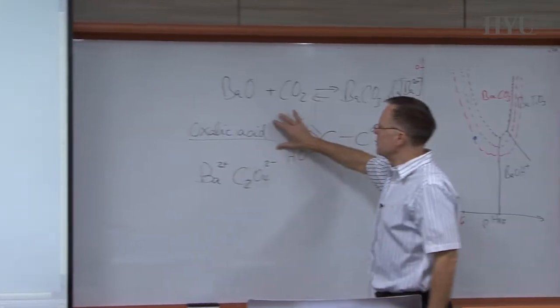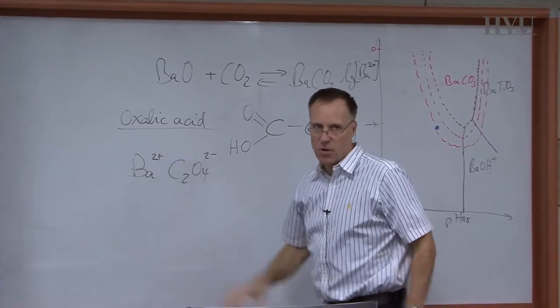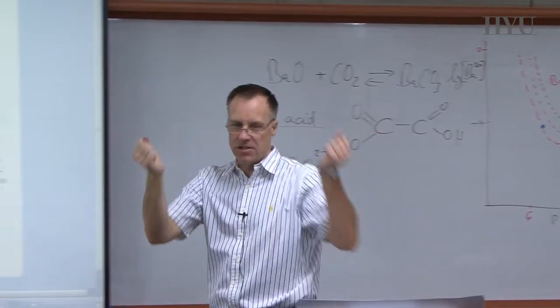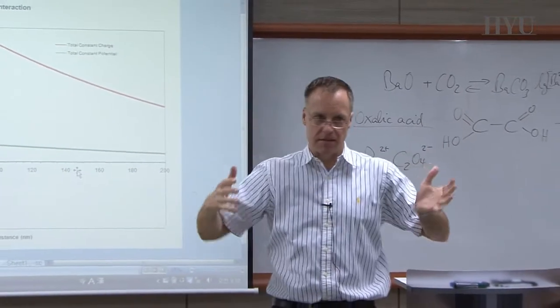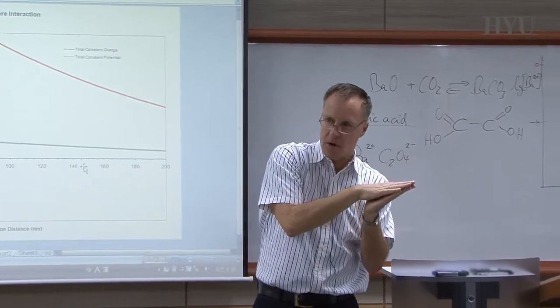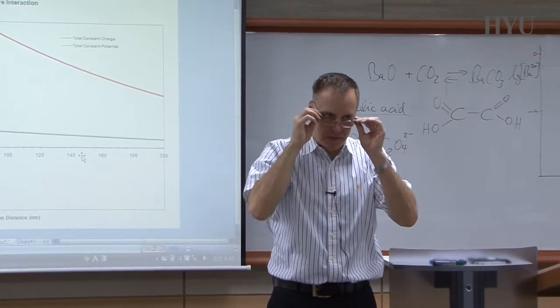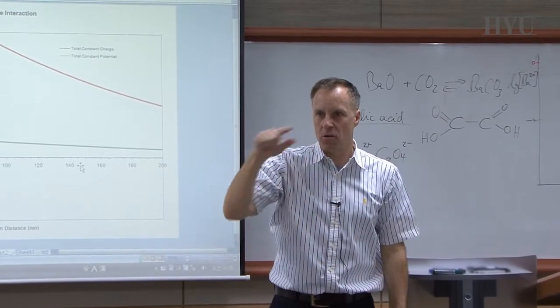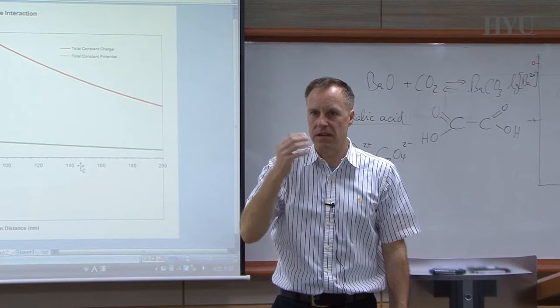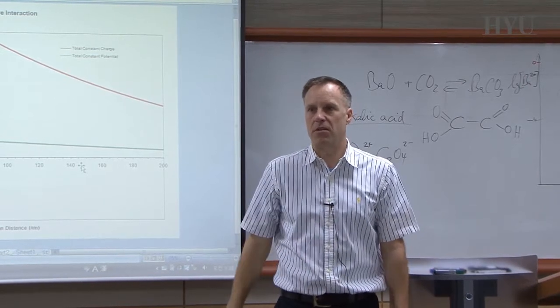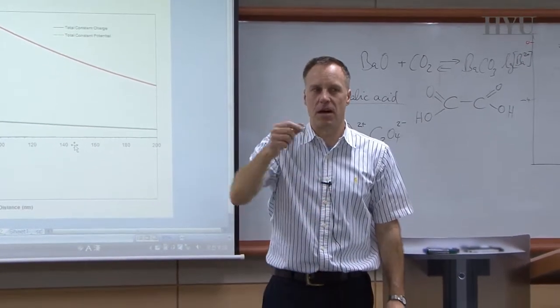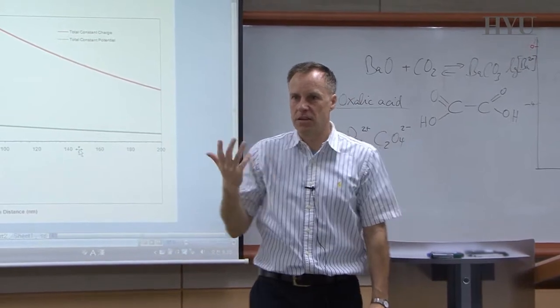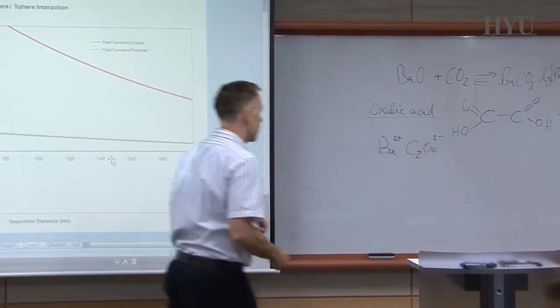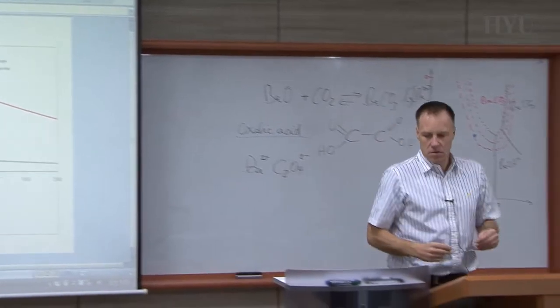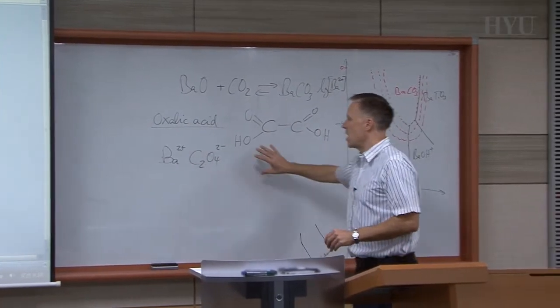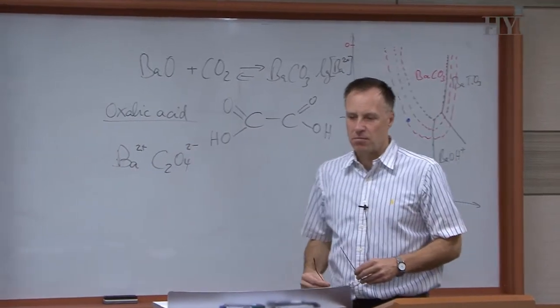And oxalic acid, because it precipitates this, it actually forms a barrier layer. Basically, barium leaches out, oxalic acid is present. You precipitate barium oxalate on the surface of your barium titanate particle, and you get a coating. The coating is dense enough that you hinder leaching of further barium. And if any further barium comes out, it will precipitate also. So it's actually a pretty good process to do that. So we have now a chemical reaction where you can block that.